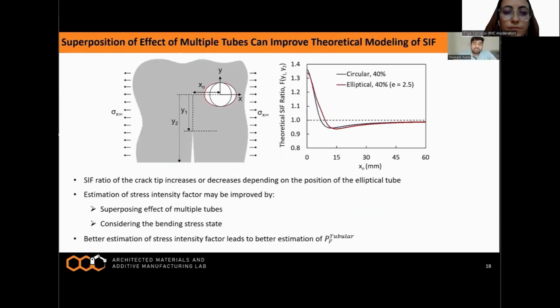The theoretical analysis that I showed before for the stress intensity factor was conducted for a single tube. The superposition of multiple tubes and the positive and negative effects of their location on the stress intensity factor can be considered to better capture the experimental analysis. It is also interesting to note that the SIF ratio of the crack tip increases or decreases depending on the position of the tube from the crack tip. The theoretical determination of the stress intensity factor can be extended for better comparison of experiments and analytical model, considering both the superposition of the effects of multiple tubes at various locations ahead of the crack tip, as well as the bending stress state.